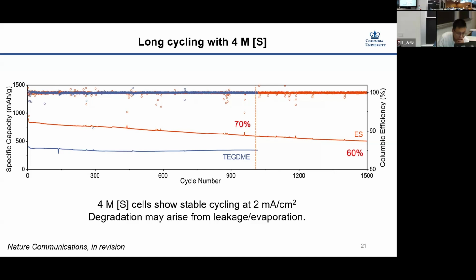We further try to optimize the cell and demonstrate long-term cycling. All these cells are in pouch-cell regions, and the loading on the cathode is roughly 3 milligrams per square centimeter. You can see about 1,000 cycles right now with 70% capacity retention. We are still doing more optimization. And the degradation, I think, is mainly derived from leakage and evaporation of the solvent.